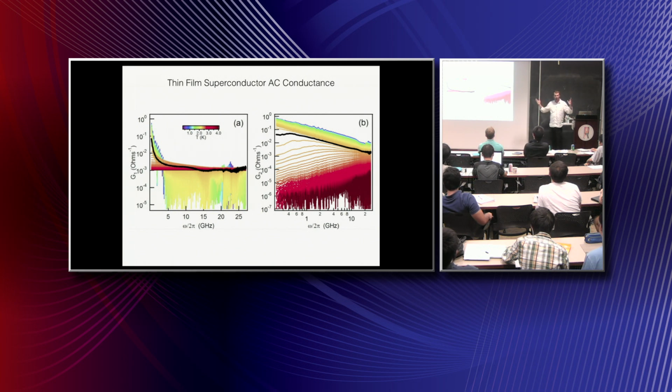So there are superconducting fluctuations. We can think of these heuristically as bubbles of evanescent superconductivity forming, holding on for a moment and then dissipating, and the material becomes a better and better conductor. These bubbles form for longer and longer periods of time over longer and longer length scales until eventually the time scale diverges to the length of a PhD thesis, and that's the superconducting transition. Here, this can be plotted in units of inverse PhD thesis, its frequency, and so what you see is this maximum directly represents critical slowing down of these fluctuations as you go to the superconducting state.